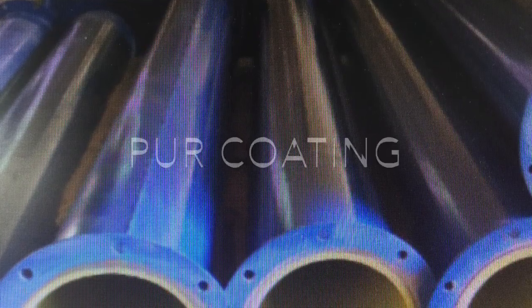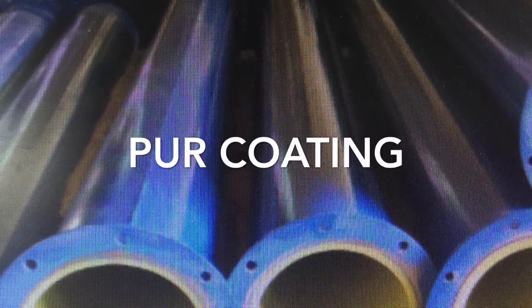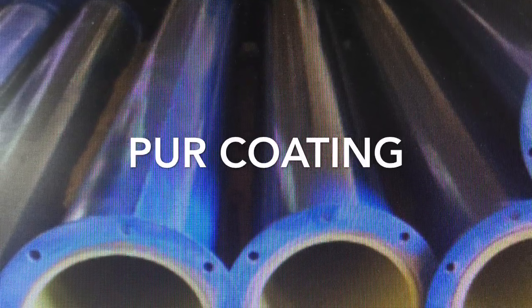Material selection is one strategy to address corrosion. Corrosion control can be designed into the ship itself. Using high-quality coating systems is another strategy for battling corrosion on the ship. The main deck is protected with a high-grade combined composite coating system that starts with a zinc primer, followed by an epoxy coating with aluminium pigment as the second coat, and then a top coat of PUR coating.